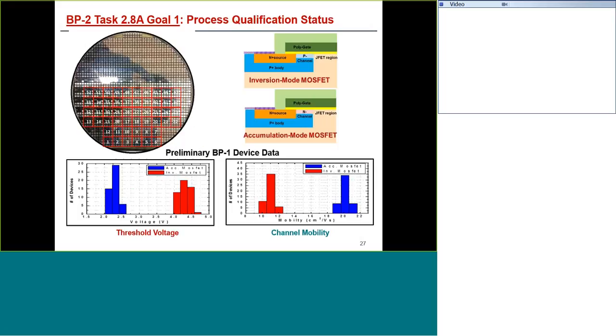Okay, so as I said, those wafers have not run because of wafer supply. So instead, while waiting for them to run, we took the BP1 wafers and started doing some statistical measurements. These measurements were taken by hand by my student on individual die before we installed our automated probe station. So this is taken very tediously, but at least we have a sampling of about 50 sites.